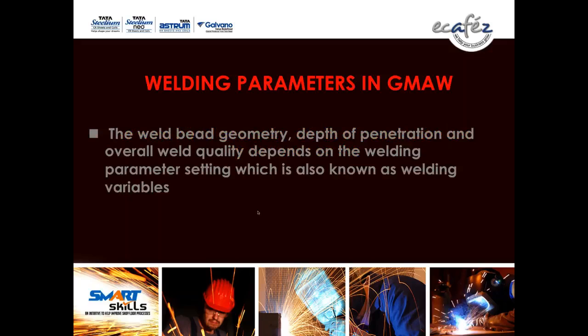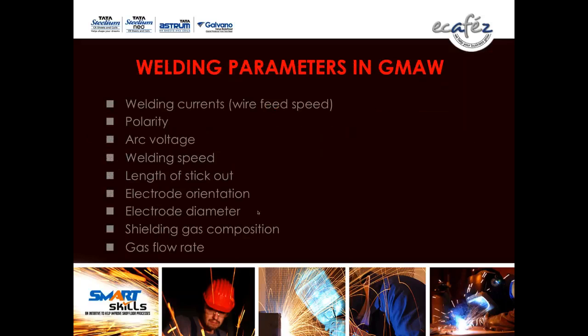The weld bead geometry, depth of penetration, and overall weld quality depend on the welding parameter settings, which are also known as welding variables. Welding parameters in the GMAW process depend on the following. Welding current, which is also related to the wire feed speed, polarity, arc voltage, welding speed, length of stick out, electrode orientation, electrode diameter, shielding gas composition, and gas flow rate. These are very important parameters in the MIG process.